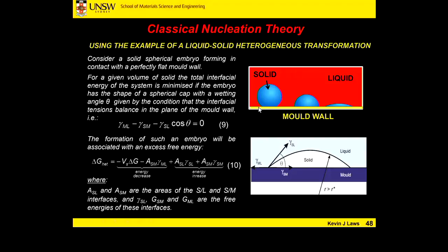Basically, for a given volume of solid, the total interfacial energy of the system is minimized if the embryo has the shape of a spherical cap. So this is the assumption that we're going to make again for this spherical case. This sphere is going to have a specific wetting angle, theta, given by the condition that the interfacial tension is balanced in the plane of the mold wall.